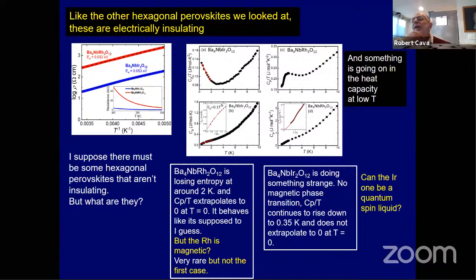But basically we end up with two things, an iridate version of this trimer, which is a 5D trimer, where the specific heat at low temperature is really bizarre. It goes up to 0.35 Kelvin, which is as low as we can measure it. So this iridium one, you know, the heat capacity of matter should go to 0 at 0 Kelvin. That's one of the rules of thermodynamics. But in magnetic systems that have bizarre magnetic ground states, you can have magnetic entropy left at really, really low temperature. And the iridate has magnetic entropy left in it at 0.3 Kelvin. The rhodium looks more normal, like it's lost its magnetic entropy, but hasn't quite lost all of it.